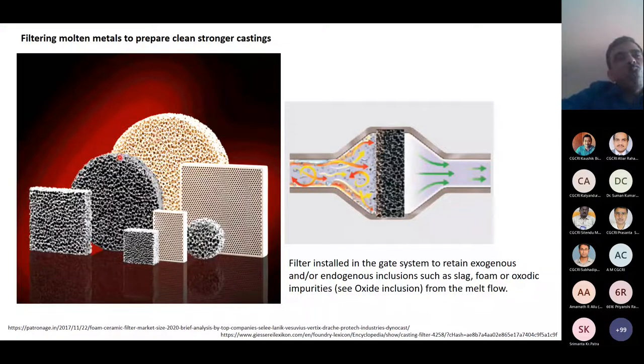In this case, when you have molten metals and when you need a very clean metal casting, you put that in between and it allows the metal to pass through and retains a lot of impurities. And what you get, which you cast, is a cleaner metal, which has basically higher strength. So again, high temperature materials enable that, and there are other characteristics also required. But very interesting how these are made, if some of you get curious, these are called reticulated foams, by the way. And these are made from polyurethane sponge. So you start with a polyurethane sponge and you finally make these rigid, highly porous ceramic foams.